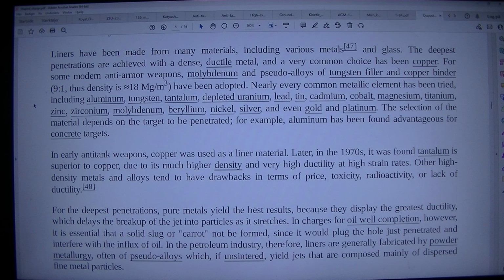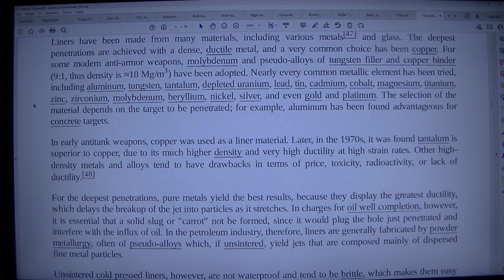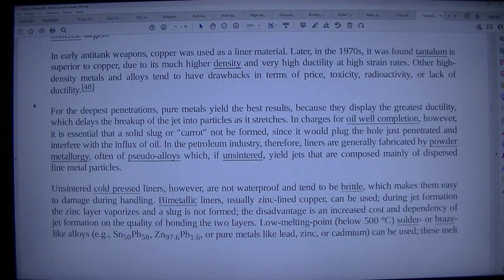The selection of the material depends on the target to be penetrated. For example, aluminum has been found advantageous for concrete targets. In early anti-tank weapons, copper was used as a liner material. Later, in the 1970s, it was found tantalum is superior to copper, due to its much higher density and very high ductility at high strain rates. Other high-density metals and alloys tend to have drawbacks in terms of price, toxicity, radioactivity, or lack of ductility.